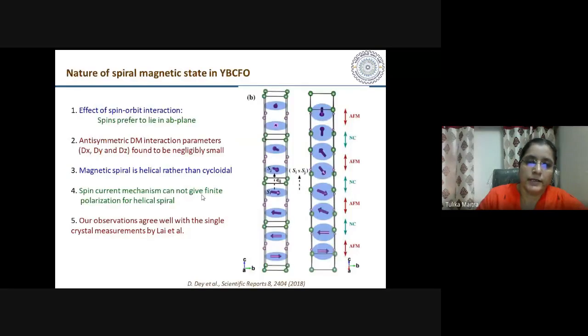Okay, and also we calculated the Dzyaloshinskii-Moriya interaction, and what we found here is that all three components of the Dzyaloshinskii-Moriya interaction are negligibly small. By performing calculations with spin-orbit interaction, we found that spins actually prefer to lie in the plane rather than going out of the plane. So this state has lower energy compared to spins which are out of the plane. So this is the most probable ground state structure in the incommensurate phase. And if this is the case, then the magnetic spiral state is helical rather than cycloidal. Okay, so we established that this spiral state is not cycloidal, but it is helical.